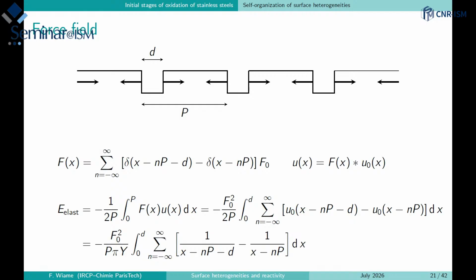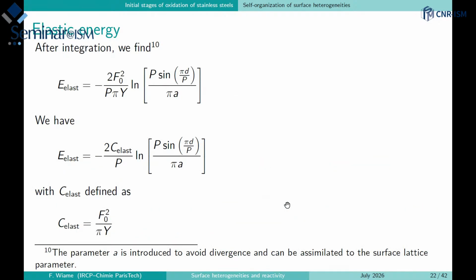The force field, as I told you, we will have some force at every atom that is not linked. So at every side atom of the vacancy, we will have a positive force. These point forces we can simulate by a Dirac distribution. And so we have the positive force here, here, here, and we have the negative force at this position. If we calculate the displacement, which is just the convolution of this force field with the displacement for one point force, then we can calculate the elastic energy, which is the integral of the sum of the inverse, which will give you the sum of logarithms, which will give you the logarithm of a product, and this product can be simplified and give you some function like this. So this elastic energy will depend on the periodicity of your system.